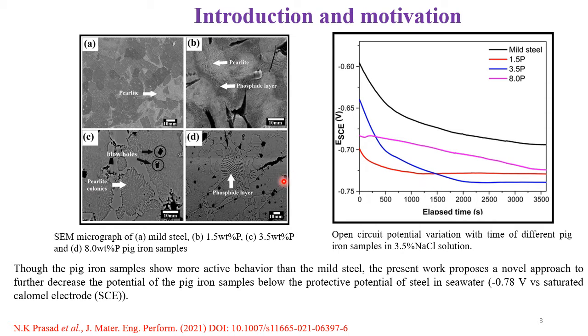And in different environments like seawater, soil, and concrete, they have also satisfied the 100 millivolt polarization decay criteria for a sacrificial anode. However, industrially it is recommended that the steel which is to be protected needs to be polarized more active than minus 0.78 volt versus the saturated calomel electrode, which was not observed in our previous study. So in the present study, we have come up with a novel technique of incorporating a small amount of zinc into the pig iron powders to achieve this protective potential or the cathodic protection criteria.